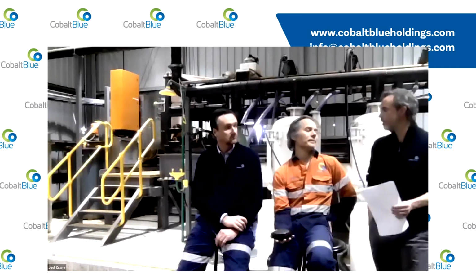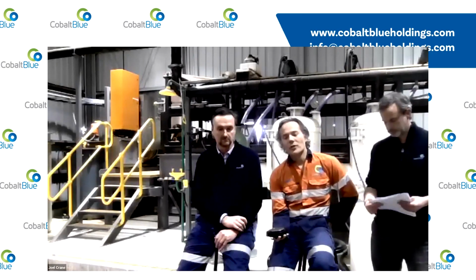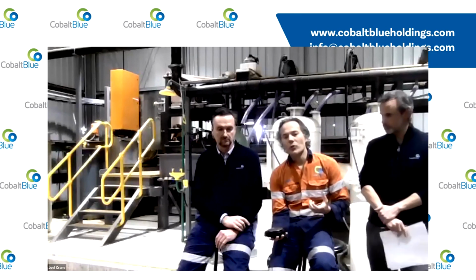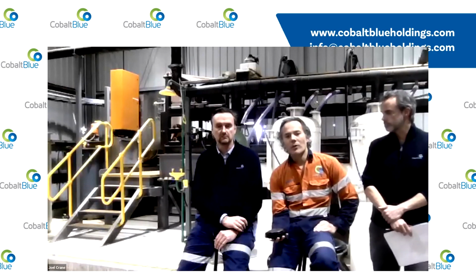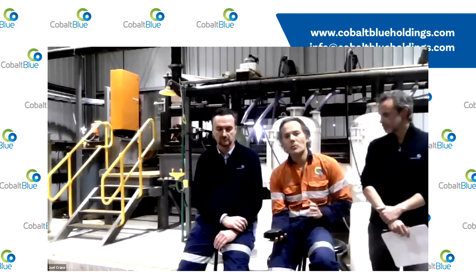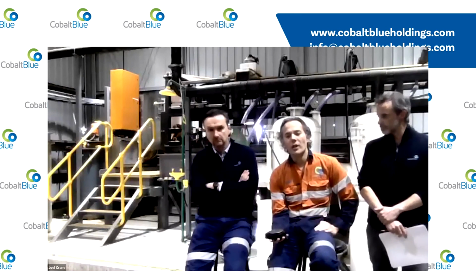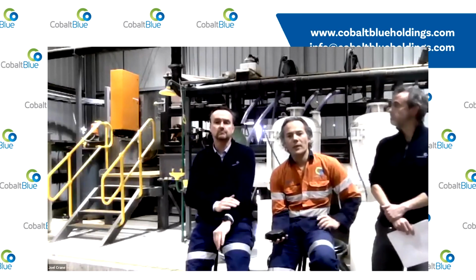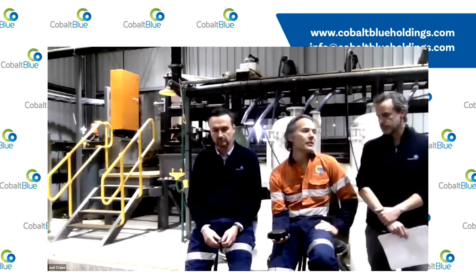And how's the concentrate looking, Andrew? So far on the concentrate side, we're producing fairly coarse grain pyrite concentrate, as we would expect. We're still tweaking some of the recovery parameters in terms of the spiral cutters between the waste and the pyrite concentrate. And we've got a little float cell there picking up all the fines. Overall, the concentrate's looking excellent.